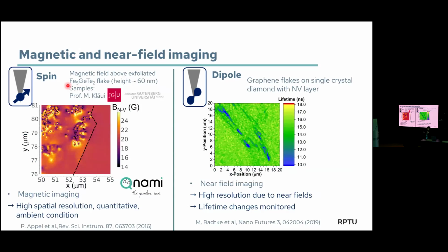And interestingly, it's not really known how these magnetic properties change with the thickness. So you can make flakes of different thickness, but in the end, you don't know if you have a multi-domain or a single domain. It's ferromagnetic, yeah, but you don't know this domain structure. And this is why we started this collaboration, because often when people are working with these materials, they make devices out of it. This goes especially in the direction of spintronics. And then they are measuring with transport measurements, for example, and they integrate over the whole flake. Now you get something out, you make a device again, and you get something totally different out. And then you're asking yourself, why?